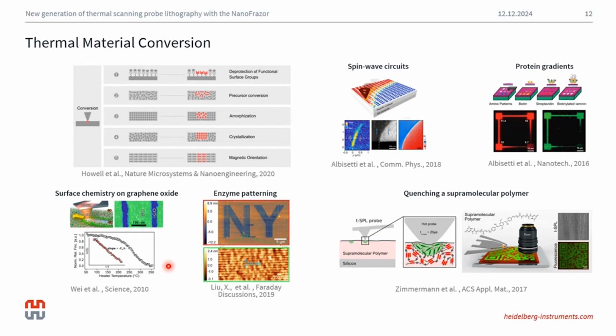In this example here, the NanoFrazor heated tip was used for the local thermal reduction of graphene oxide. In this way, the tip could pattern regions down to 12 nanometers in width that are up to 4 orders of magnitude more conductive than pristine graphene oxide. In the second example, the heated NanoFrazor tip as well as light from the laser writer head were used together to directly induce controlled and localized changes in the magnetic landscape of thin films. If you'd like to learn more about these methods in particular, then you could watch the NanoFrazor webinar by Professor Eduardo Albisetti and get more details.